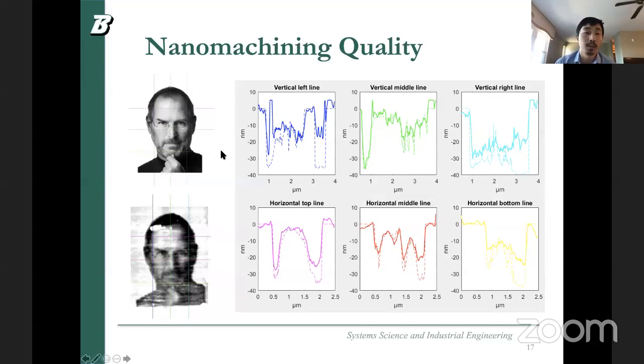pattern. As we can see, a lot of details have been lost because of these tiny unmatched areas. You see, there are many reasons for generating these tiny unmatched areas. One reason is some vibration and some sharp angle, because, as you can see, these are almost 90-degree vertical walls.